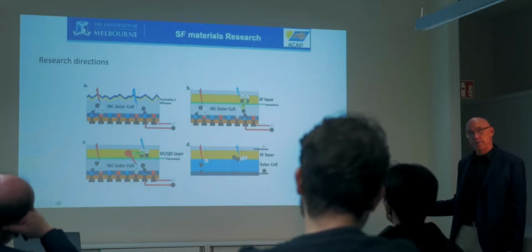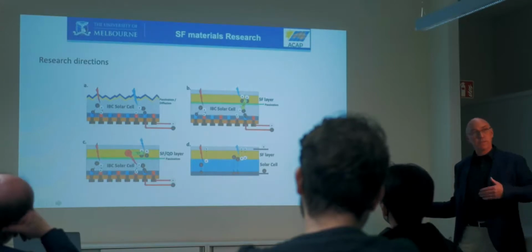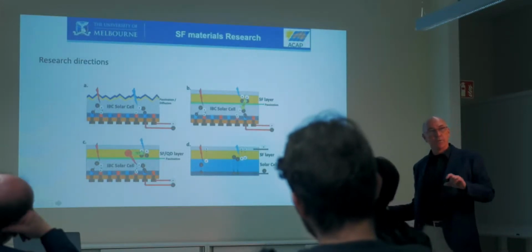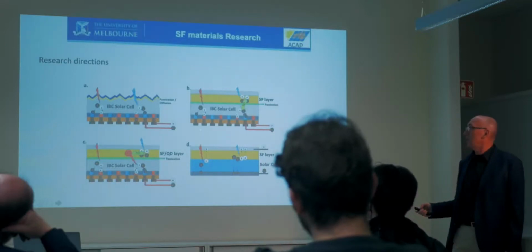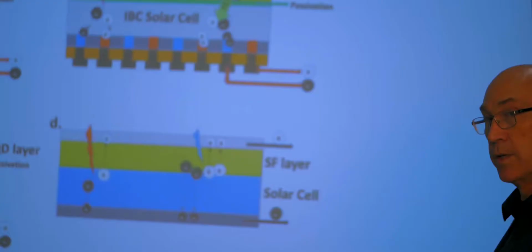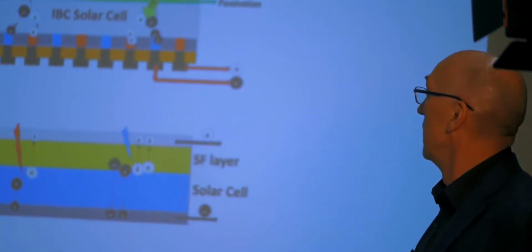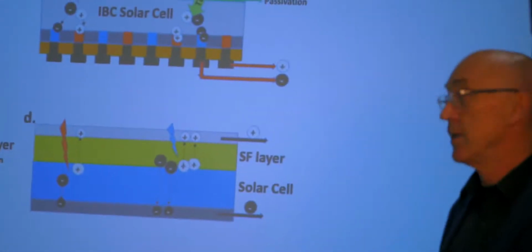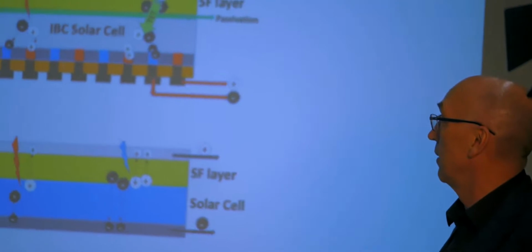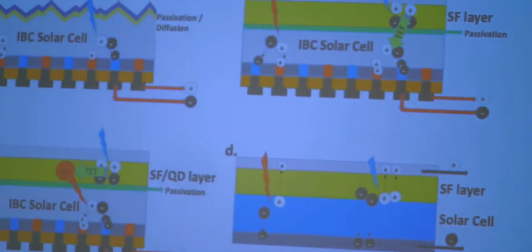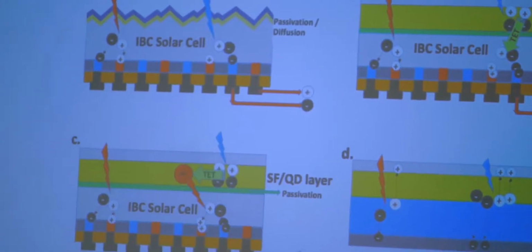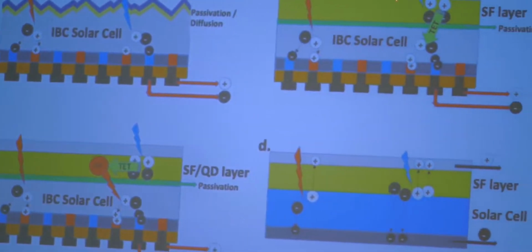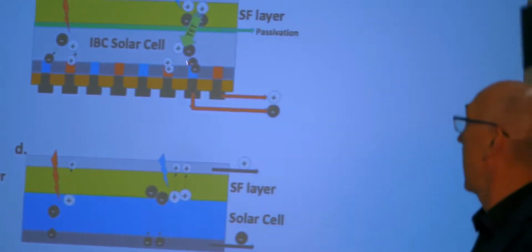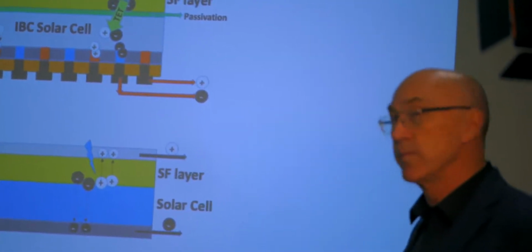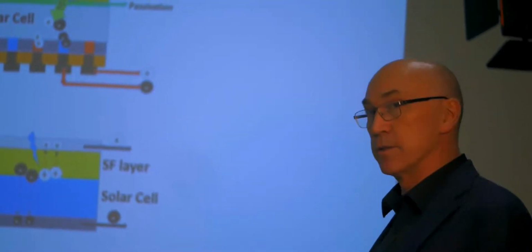So we've basically got the silicon solar cell, and therefore that tells us we want to change our triplet energy level to energy match silicon. We need to design and make that, and we've done a lot of that. We need a passivation layer here, which is not going to destroy the function of the silicon solar cell, and then we're going to put our singlet fission layer on the top. So now instead of both the low energy and the high energy photons going into the silicon, the low energy photons will go straight into the silicon solar cell. The high energy photons will be trapped by our singlet fission material and will generate triplets, and then this passivation layer is very thin, and we can do energy transfer into the solar cell.